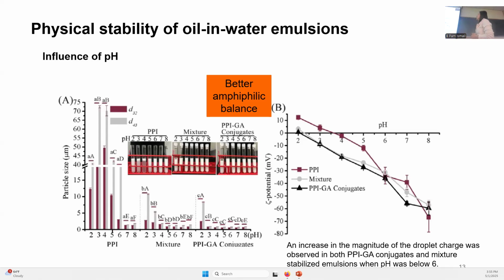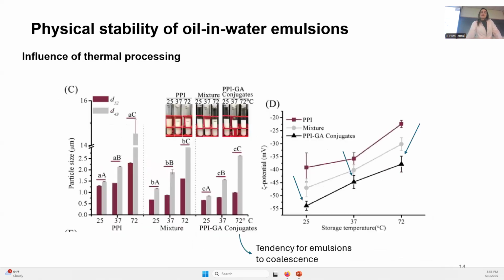And then when we look at the charge, we can see an increase in magnitude of the droplets for both the conjugates and the mix when the pH was less than 6. And another thing that the author says is that this increased stability compared to PPI is because of the steric hindrance provided by the gum arabic. Then they also looked at the influence of thermal processing. So they made the emulsions and incubated them at different temperatures, 25, 37, and 72 degrees Celsius for 24 hours. And they evaluated the particle size and the charge again.